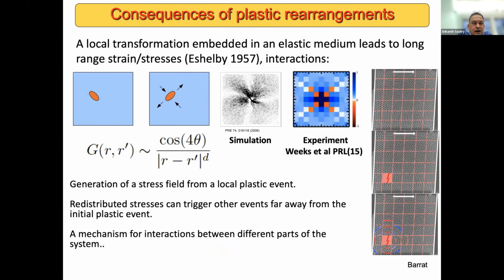Now, when one such local transformation takes place, and if one imagines the rest of the system as being a linear elastic medium, one has an understanding of what happens. And this is going back to the work of Eshelby, one expects that such localized rearrangements will lead to a propagation of stresses which are long-ranged and have a particular form that has been both observed in computer simulations and experiments, and therefore fairly well understood. And these stress fields can lead to interactions between different parts of the system and trigger other events away from the site of the initial plastic event. And how this leads to yielding behavior is something that one would want to understand.